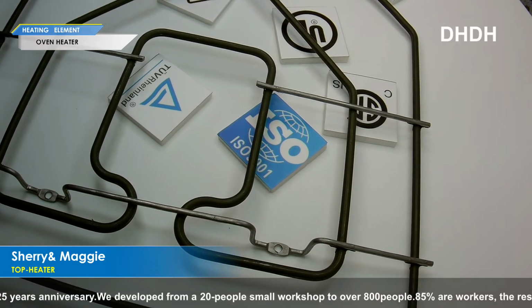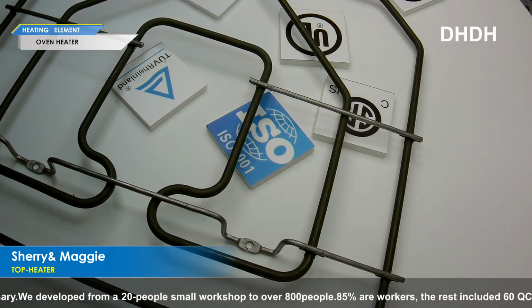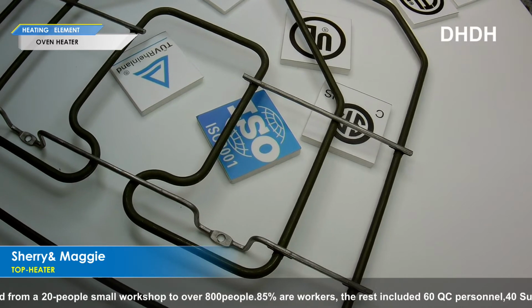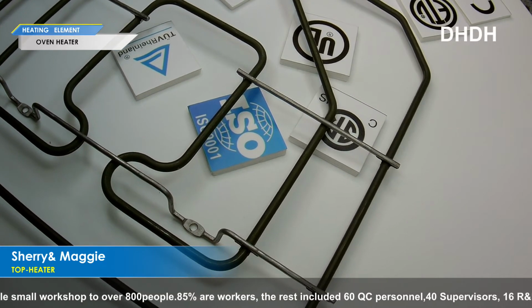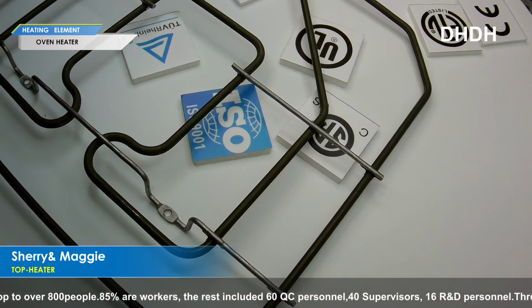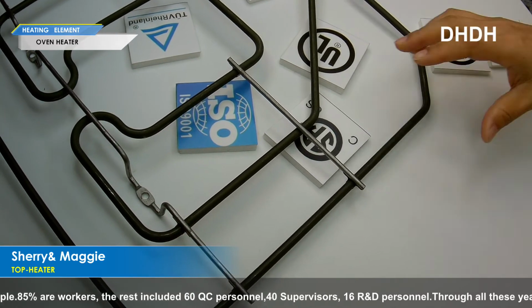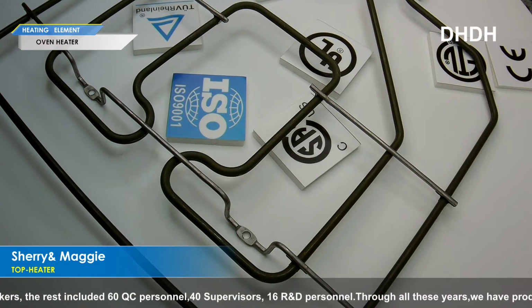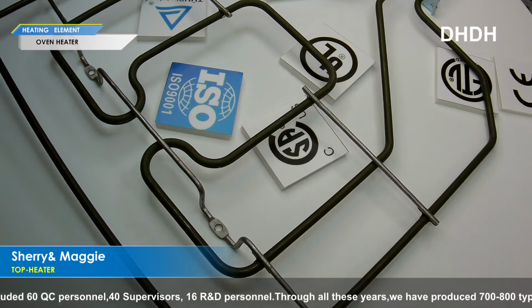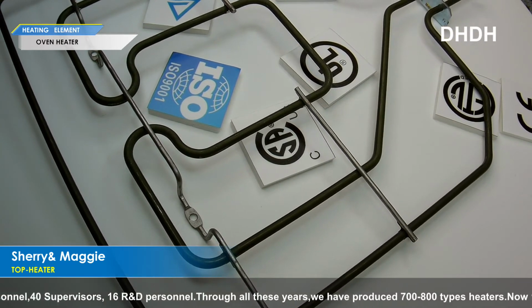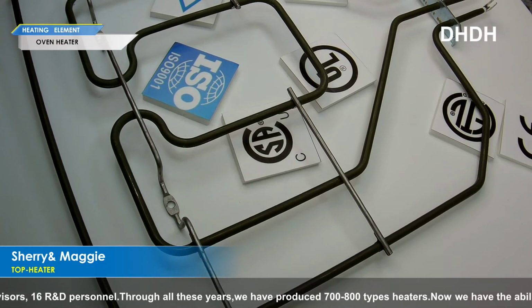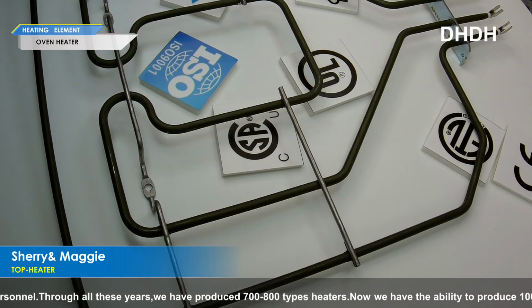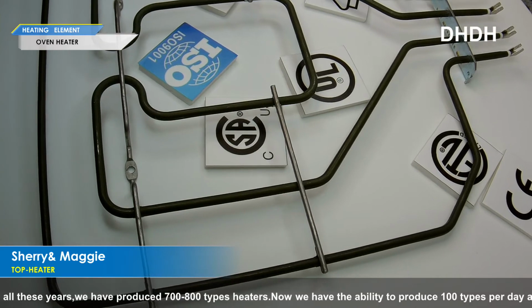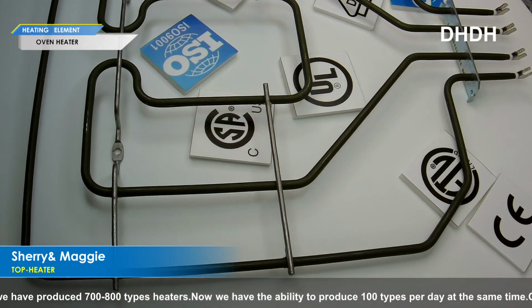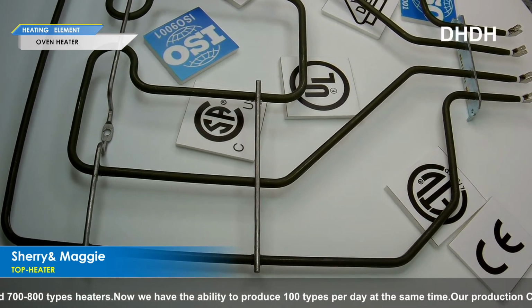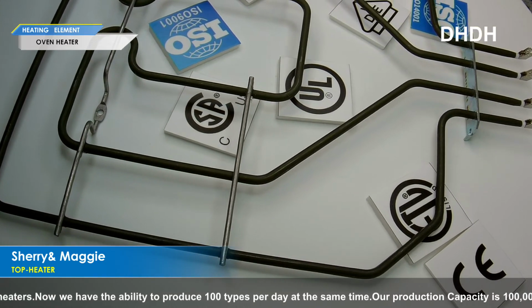When they gather together, the oil will carbonize, and then the tube will burst very easily. So it's dangerous. And we also call this heater a fake heater because the MgO is unqualified, even though the annealing color is the same as the true one. So you can say the different MgO you use will make a big difference to the heater performance.